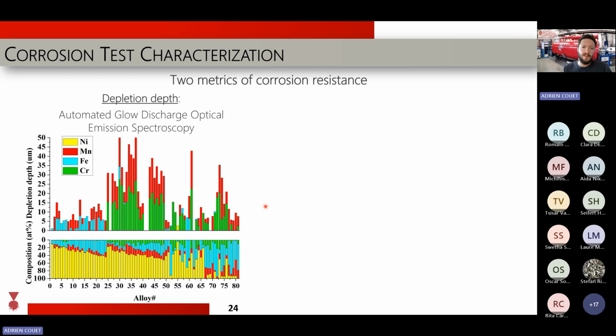And the issue with this method is that you can have an alloy that has a very small amount of an element, but a very high depletion depth of this element, right? And at the end, not much will be dissolved in the salt, even though you have a very high depletion depth. So this metric of corrosion was not working very well for us, even though we were learning interesting things. It was not a very good one to transcribe for a machine learning application.